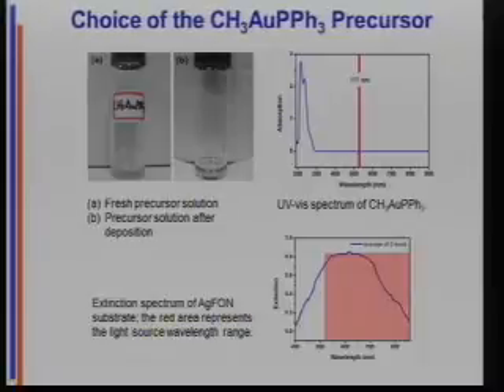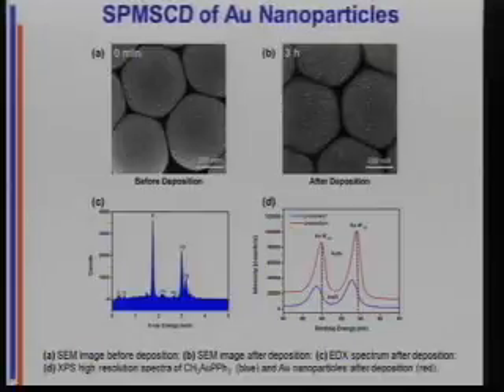And this is the extinction spectrum of the substrate. So this is absorption plus scattering. So here's where the long pass filter cuts off. So the lambda max for this is somewhere around, I don't know, 600 to 700. So we have lots of optical range where we can irradiate the substrate, but not the precursor. And what happens? This actually works, kind of to my utter amazement.